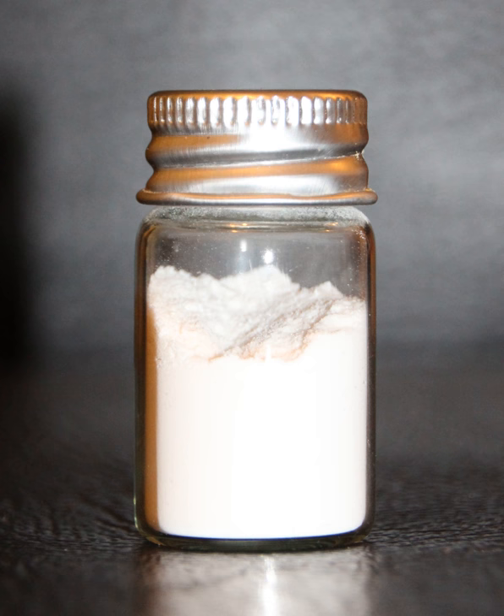Precipitated silica. Precipitated silica or amorphous silica is produced by the acidification of solutions of sodium silicate. The gelatinous precipitate or silica gel is first washed and then dehydrated to produce colorless microporous silica. The idealized equation involving a trisilicate and sulfuric acid is Na2Si3O7 + H2SO4 → 3 SiO2 + Na2SO4 + H2O. Approximately 1 billion kilograms per year (1999) of silica were produced in this manner, mainly for use for polymer composites, tires and shoe soles.